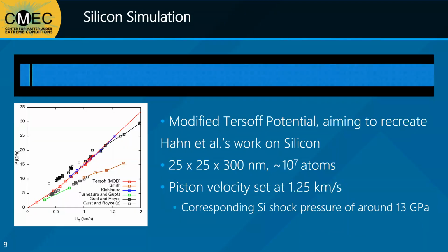The goal of my silicon research was to recreate and expand upon Zhao and Hahn's previous work on silicon. Our silicon simulation is set up in much the same way as theirs was. The bulk silicon is oriented in the 001 direction. A portion of the single crystalline silicon is cut off to use as a piston, as seen here. This block is frozen such that none of the atoms in it experience any force, but it is still able to interact with the rest of the silicon sample as it is accelerated into the bulk.